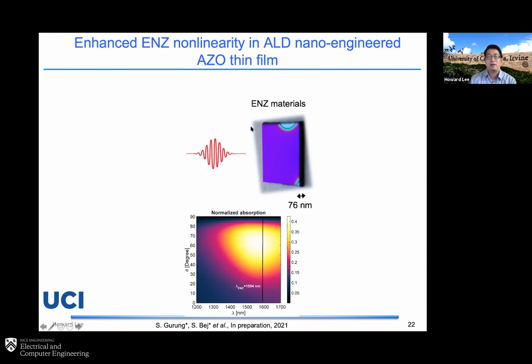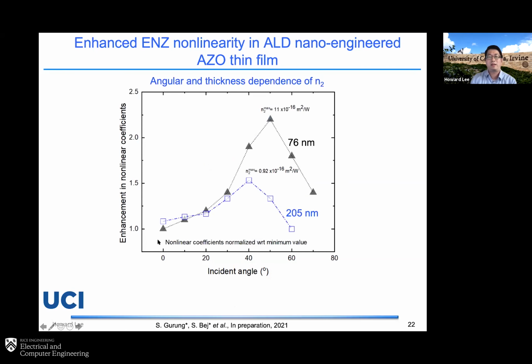And another thing is, as I mentioned to you, the ENZ mode really depends on how you excite the mode, which really depends on the angle of incidence. If you look at the absorption here, you can see for different angles and wavelengths, at certain angles you may excite the modes much more strongly so that you have a stronger absorption. That's why if you look at the angular distribution, you may see different angular dependency of the n2 nonlinearity as well. So this is what we did: we changed the angle and looked at two different thicknesses.